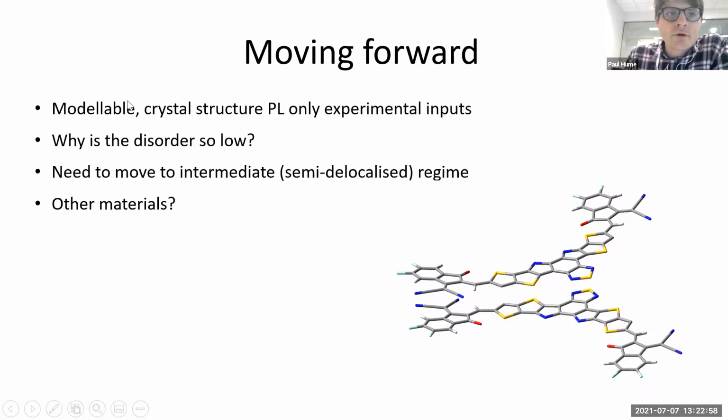And one of the main reasons it's modelable is that, even though if you calculate the total transfer rates, you don't violate incoherent energy transfer theory, you get kind of uncomfortably close at times. But I think because the couplings don't fluctuate so strongly, you stay away from the effect where thermal modulations lead to transient moments of very high coherence. And so that's quite nice from a practical prediction standpoint.